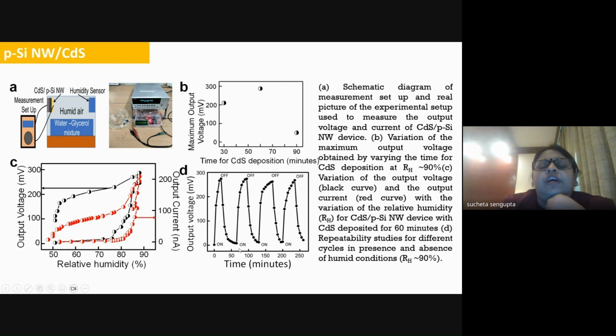The response rise time and fall time is around 50 seconds. They can be utilized to achieve a highest output voltage of around 300 millivolt, and the current is in the nanoampere range. This maximum output voltage can be varied by varying the deposition time of the CdS. If you deposit it for around 60 minutes, it achieves the highest output voltage of around 300 millivolt, and with the increase in the CdS deposition time, the output voltage decreases.